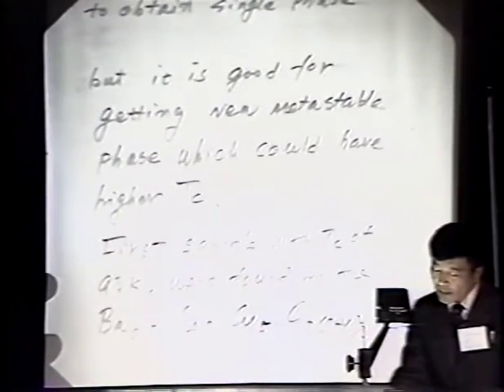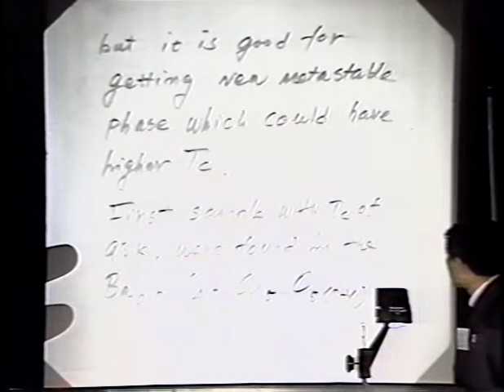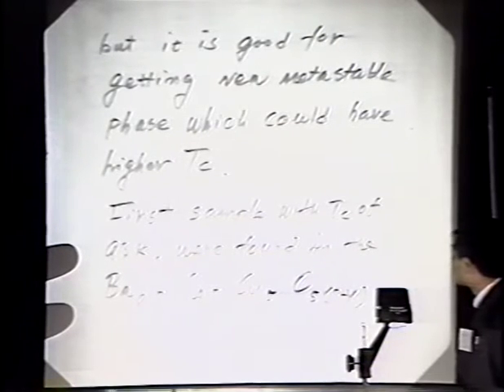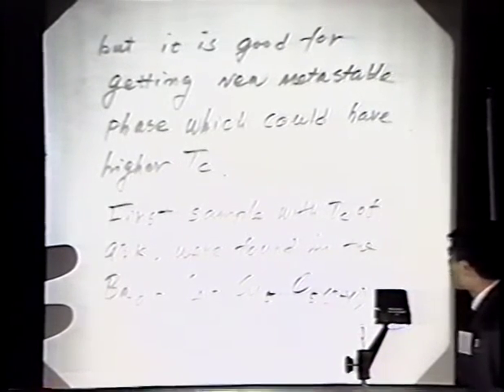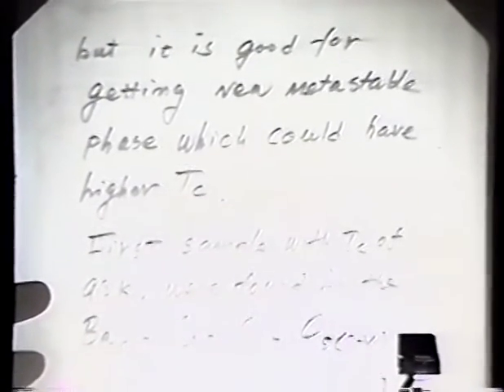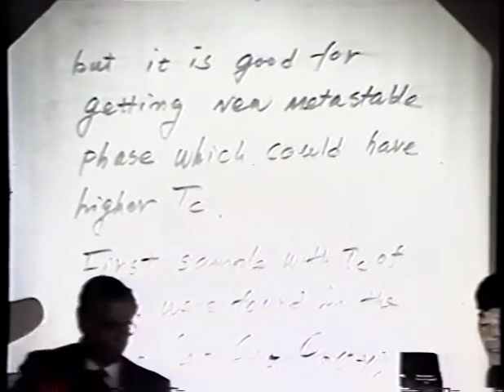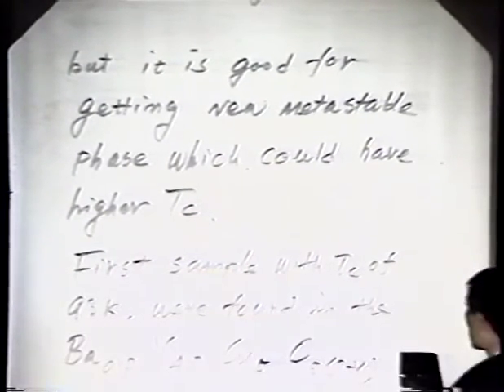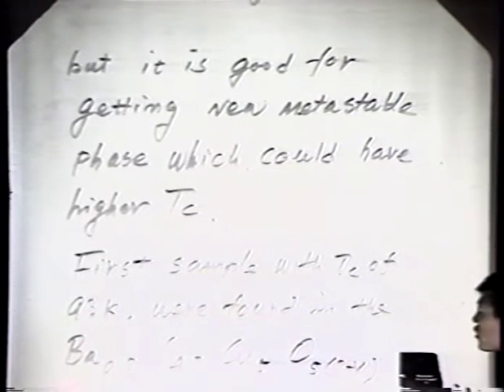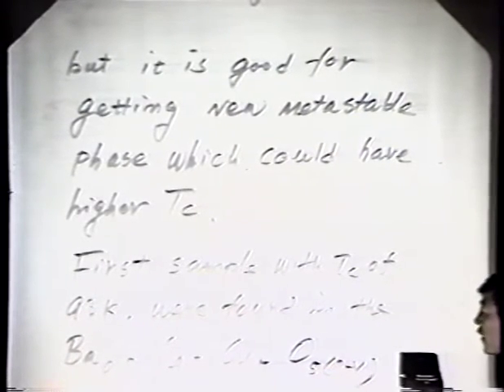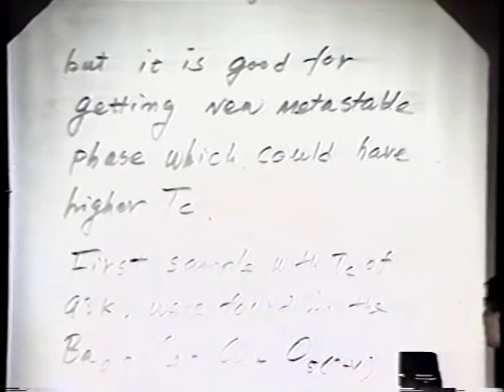We use the same formula as we did before. The first sample with the TC of 93K was found in barium 2, yttrium 1, copper 3, O7 minus y. This means it's easier to get a high TC metastable phase, even though not so much, but it is easy to find this formula.